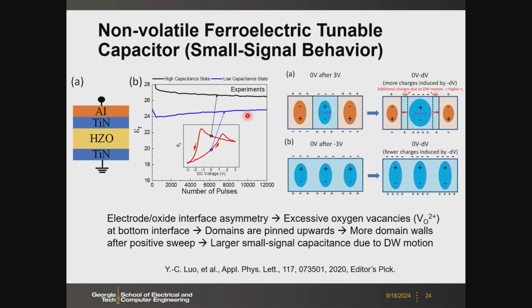So here we can keep cycling for more than 10,000 cycles. And then we suspect that in this particular sample, we have some asymmetry in the interface properties. Because we have a plasma enhanced process here, we may damage the bottom interface a little bit. Then we have more oxygen vacancy at the bottom interface. That could pin some of the domains always up, even after the forward sweep. So if we have the pinned domain after the forward sweep, then when we do the small signal CV measurements, we are going to dump more charges on the plate because of the domain wall motion. You have the expansion of the domain under the AC excitation. Then we are going to have more charges on the plate. More charges on the plate is translated as higher capacitance. Okay. So then in the negative sweep, we don't have the domain wall, then we have fewer charges.